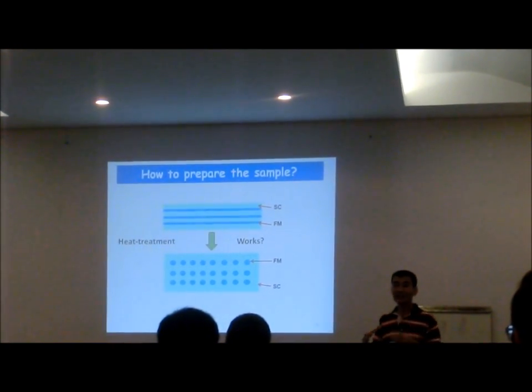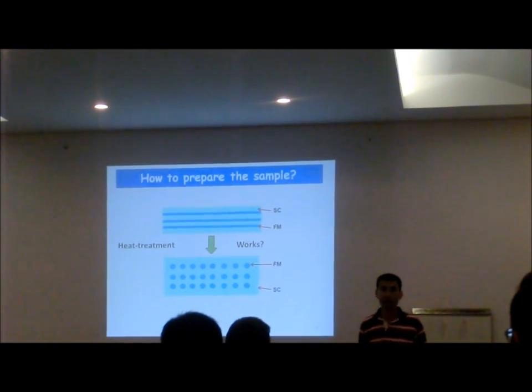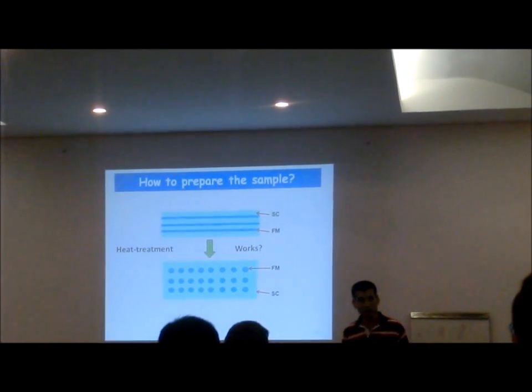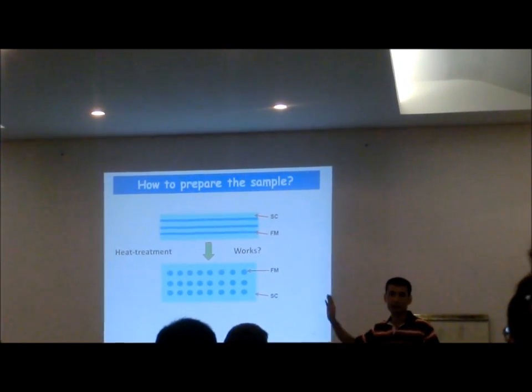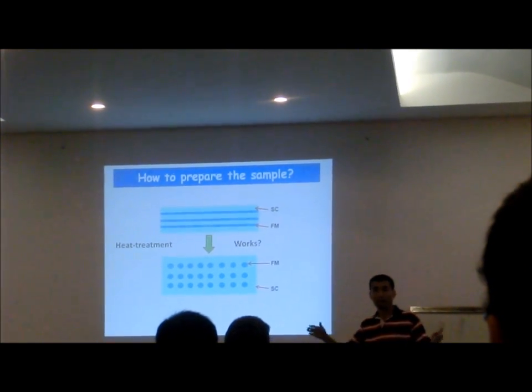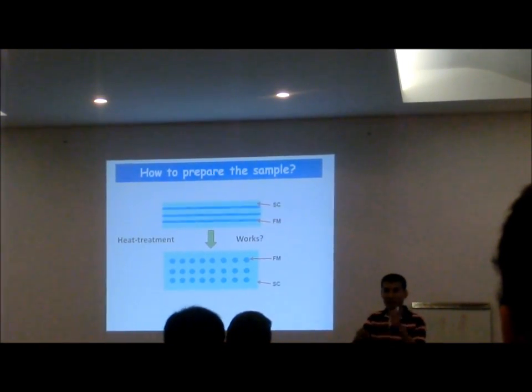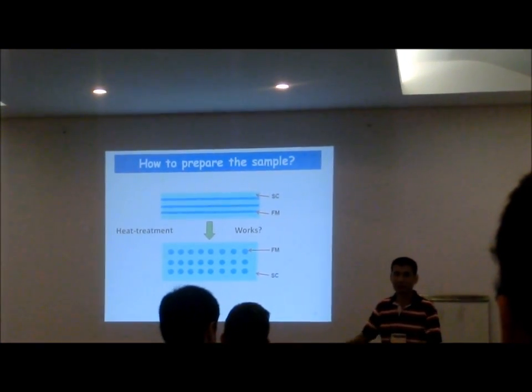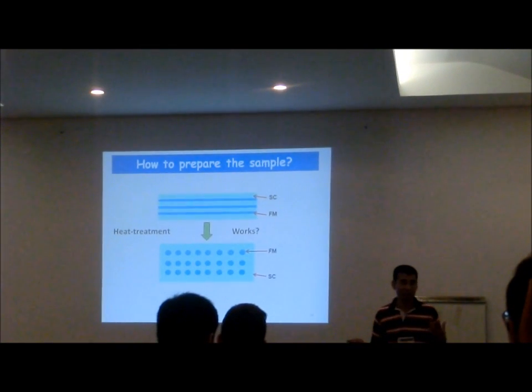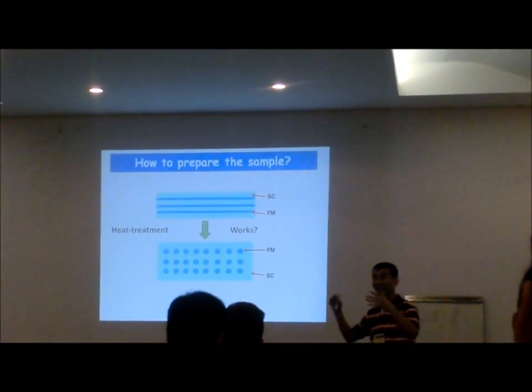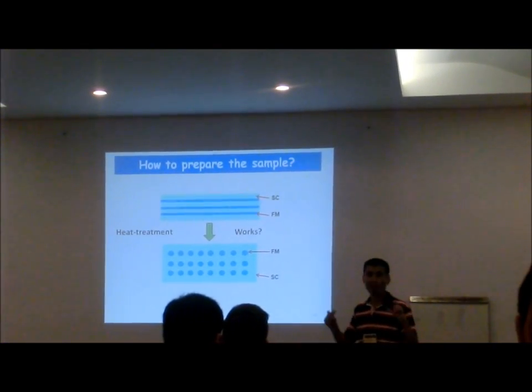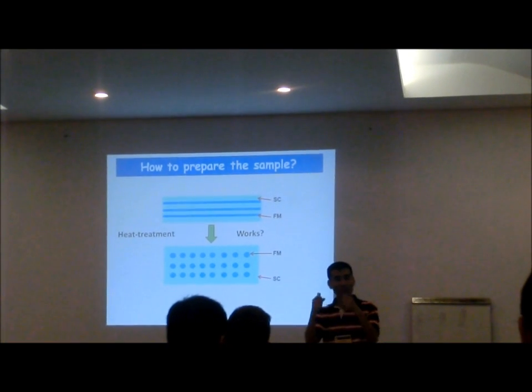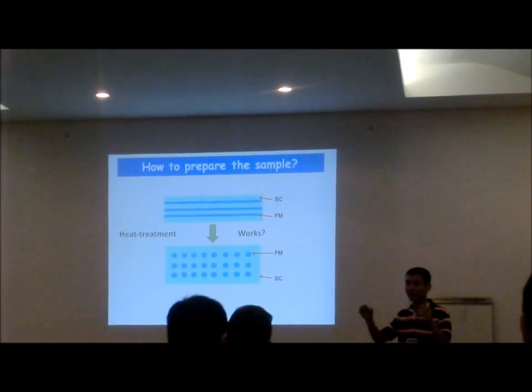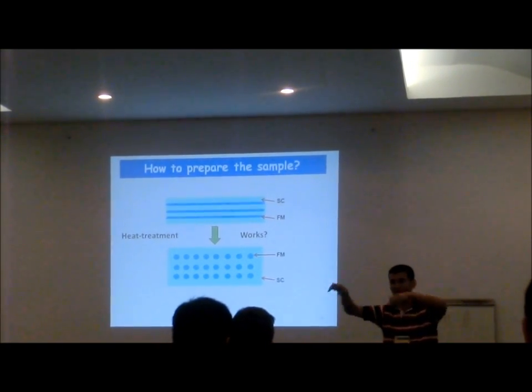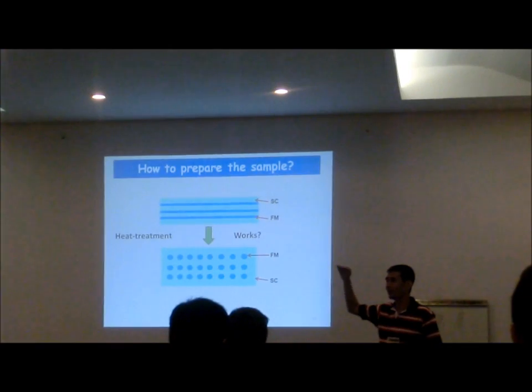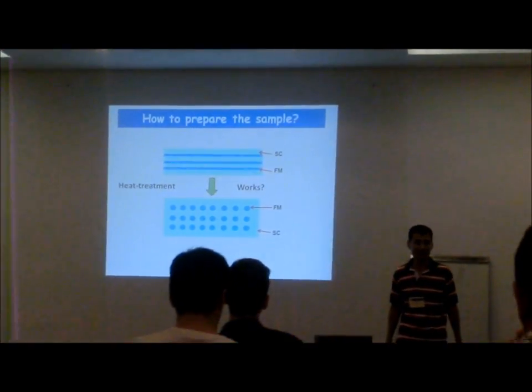With our machine, it's really difficult to prepare multiple layers. Very, very difficult because to prepare the cobalt nanoparticles, we need to put liquid helium all the time during the preparation. So we cannot prepare for a very long time. Even if we want to change the helium dewar, we have to stop the experiment. So we want to prepare, maybe, ideas. We can prepare multilayers and by some heat treatment, they may form nanoparticles. That's at least in plane it's randomly oriented or randomly distributed, but one-dimensionally, they are in order.